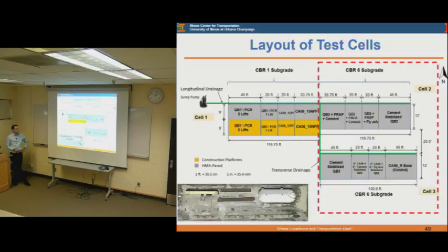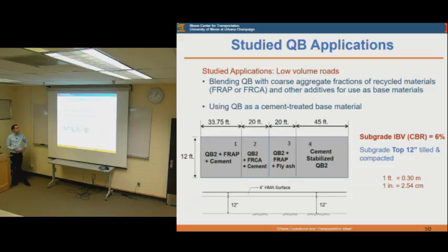And we also had some sections where we had the quarry byproducts stabilized and used as sub-base material, and topped with a regular dense graded aggregate material as a base material. So 6 inches of sub-base and then 6 inches of base material, sort of an inverted pavement application of quarry byproduct. And then at the end we had a control section, which is only 12 inches of dense graded base aggregate material. So these are the quarry byproduct applications that I basically summarized.